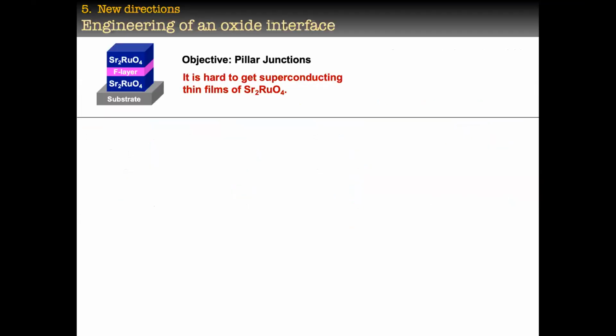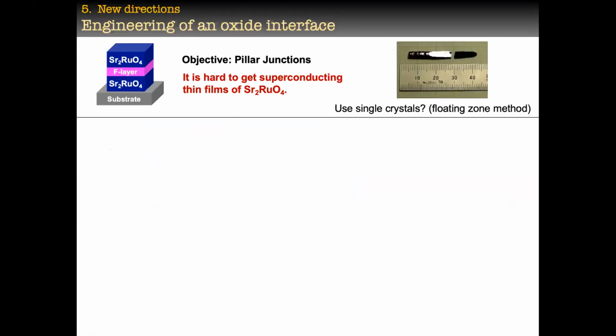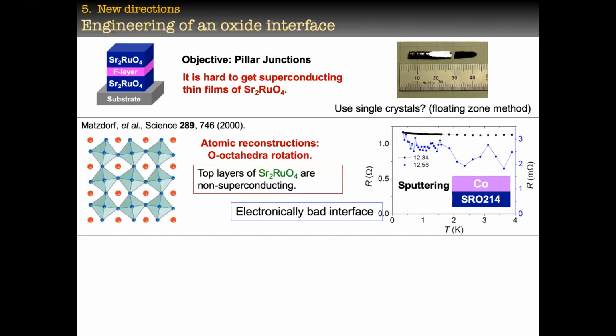When you fabricate a Josephson junction, you could simply say, okay, grow strontium-2 ruthenium-4, then a ferromagnet, then again the superconductor, and the Josephson junction will be ready. But that is not the case because we don't have thin films of this material that are superconducting, as this is a very sensitive material. What we have are single crystals. So let's try to use the single crystals, but there was again a problem.